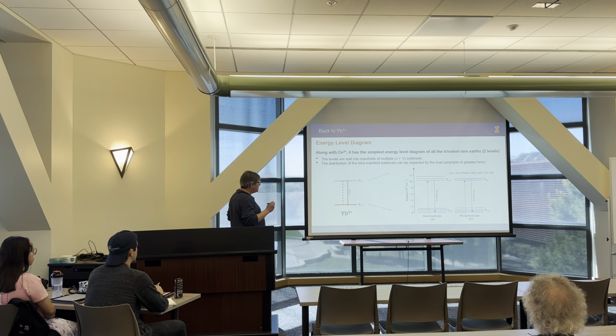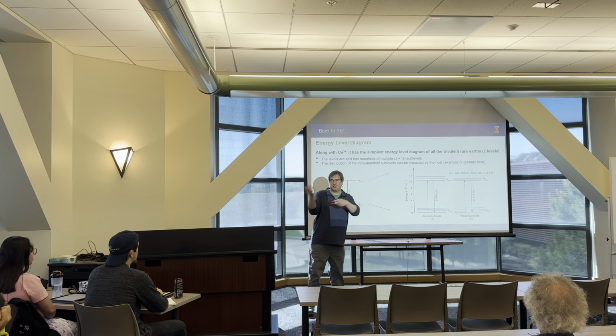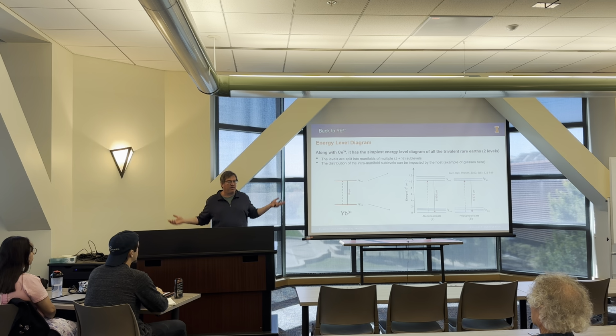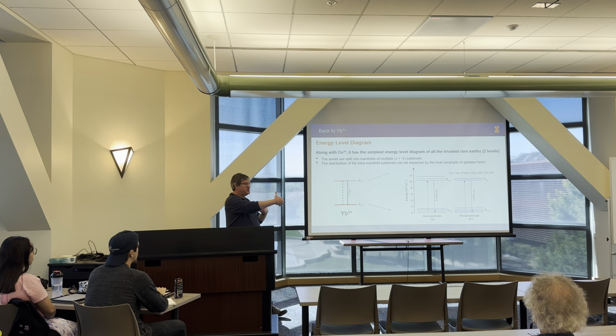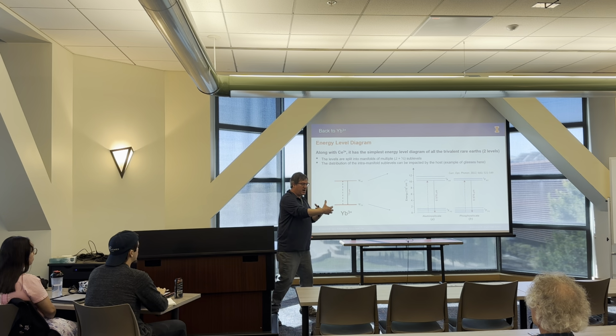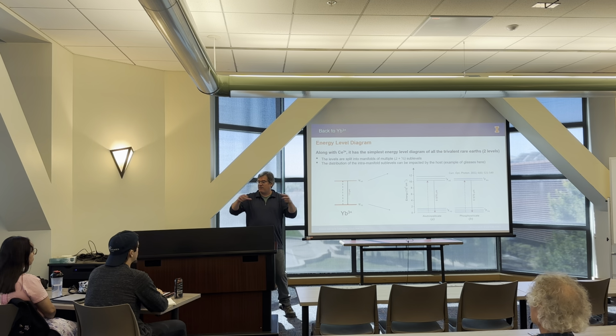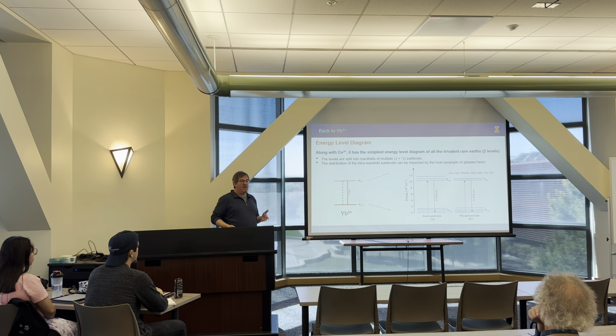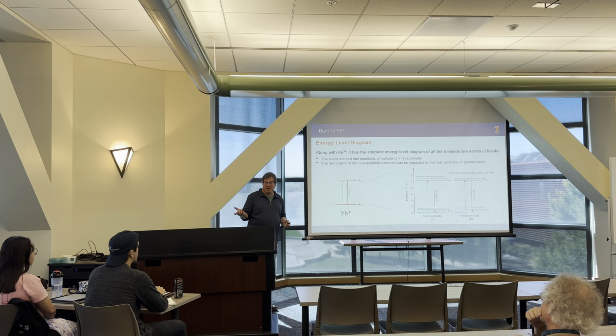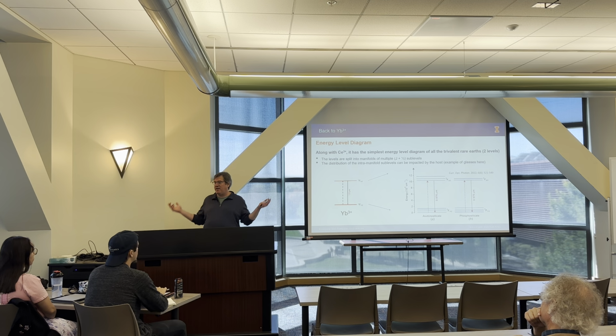Now, what's interesting about this is the rare earths aren't impacted very strongly by the host. Meaning that if you put ytterbium into this, into that, and into this other thing, you get a wavelength that's around 1 micron. It has to do with the outer shells, outside of where these transitions take place, shielding the ion from its external environment. For example, some of you may be familiar with titanium sapphire lasers. They produce 800 nanometers, peak 850 or whatever. You take that same titanium, you put it into spinel, which is a magnesium aluminate, and the peak wavelength's in the blue someplace. So it just depends on what you put it in.